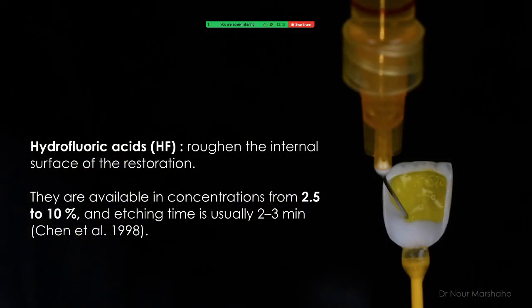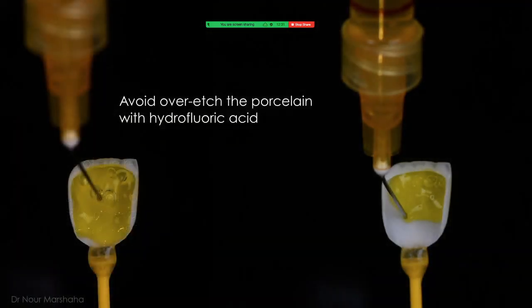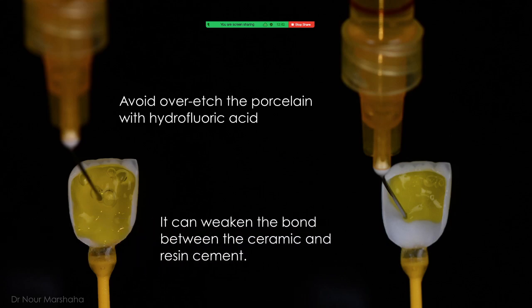Hydrofluoric acid roughens the internal surface of the restoration, and it's available in concentrations between 2.5 to 10%, with an etching time between 2 to 3 minutes. One important thing to remember is that hydrofluoric acid etchant for the ceramic is very prone to contamination with oil fluids. And avoid overetching the porcelain with hydrofluoric acid. Like I told you before, it can weaken the bond between the ceramic and resin cement.